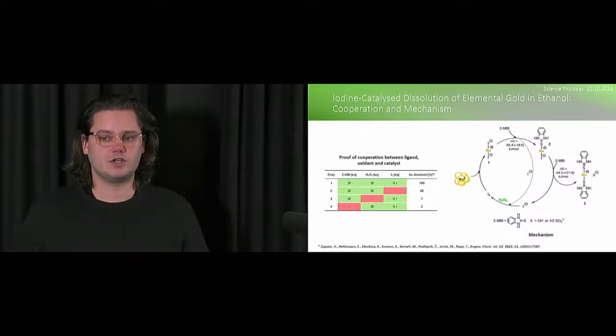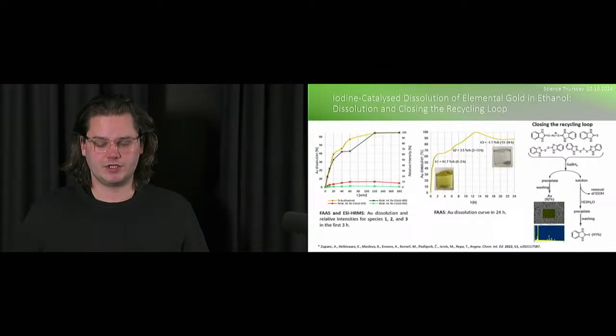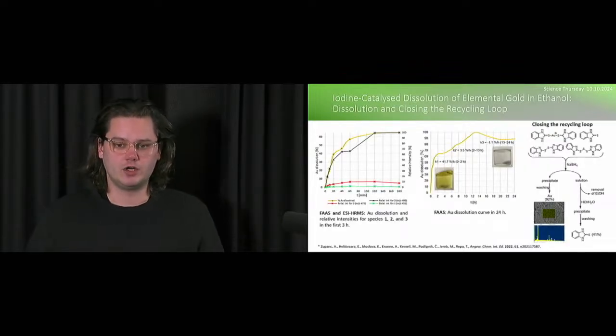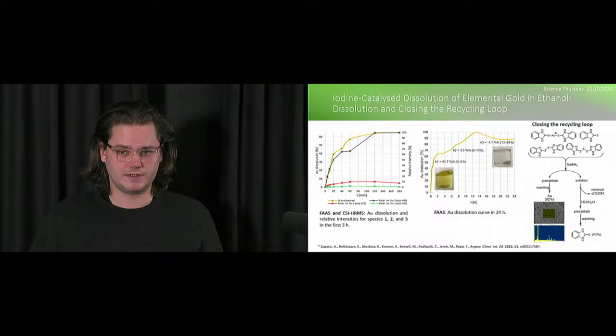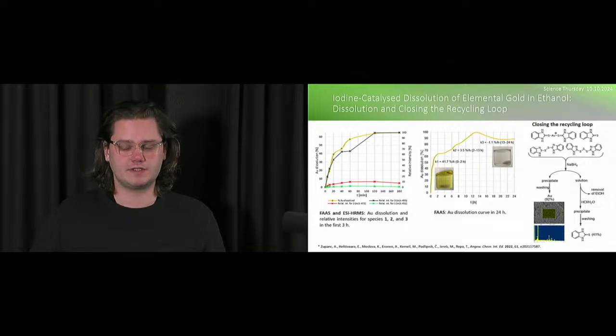But the concentration of 1 and 2, you can check them now on the slide, their concentration more or less stays somehow constant through the whole reaction. That also means that they are a part of the catalytic cycle, and the stabilized complex concentration is rising. We've been observing it for 24 hours. We saw that there are 3 different rates to this reaction, depending on the concentration of, of course, iodine that is getting recycled in this process.